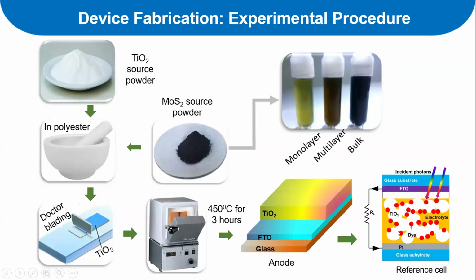If we have that, then we can directly go for device fabrication. This is the electron acceptor. Then we need to have the positive hole conductor, which in this particular case is most of the time an electrolyte. After that, we put another electrode, a high work function metal, in this particular case platinum, which is coated on another substrate. So this is the entire device structure: the glass substrate on which a transparent conductor oxide is coated, and then titanium dioxide as an electron acceptor on which the organic dye molecule is coated, covered with the electrolyte, which is basically a hole conductor, covered by platinum, a high work function metal, to regenerate the electrolyte, and then a glass substrate, which covers the entire structure. So this is the entire device structure. In this particular case, we want to introduce a 2D layered material in the second stage, while we prepare the colloidal paste, to replace the organic dye molecules.